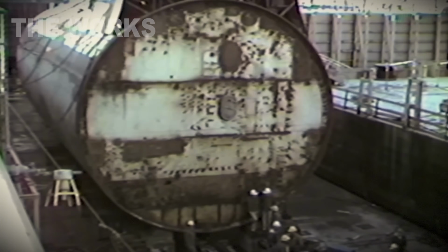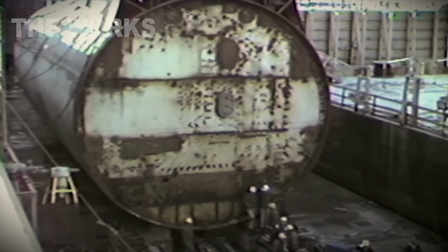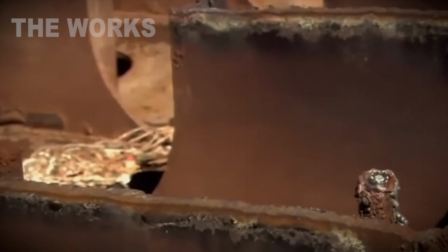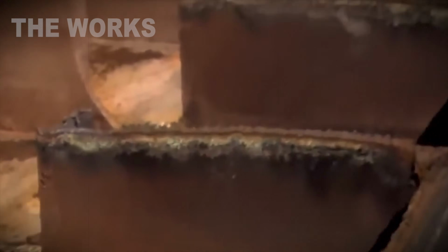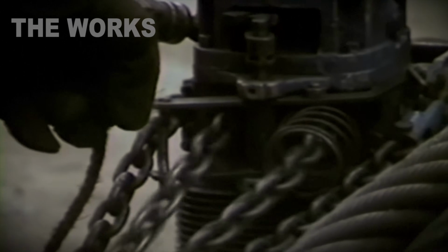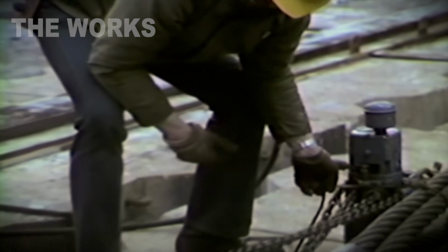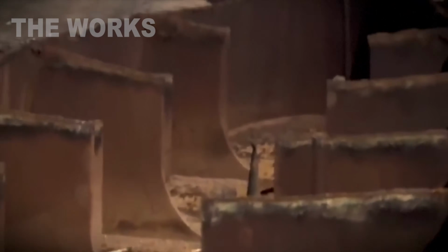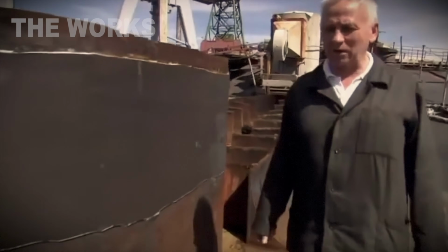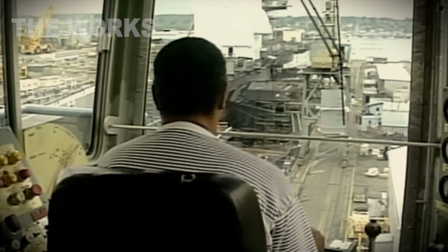They use oxyacetylene torches. Flame temperature, 5,800 degrees Fahrenheit. Mix of acetylene and oxygen. Feed pressure, 217 pounds per square inch. The torch burns through 3-inch thick steel in 10 minutes. They cut in a ring around the compartment. 2 cuts, forward and aft.